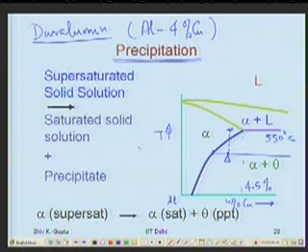If I do slow cooling, second phase will form like this. But what we do is, we take it from here, when it is all single phase alpha, quench it in water or bring it to below room temperature. So I have not allowed any copper atoms to diffuse out of the matrix. Everything remains in solution again. Right?